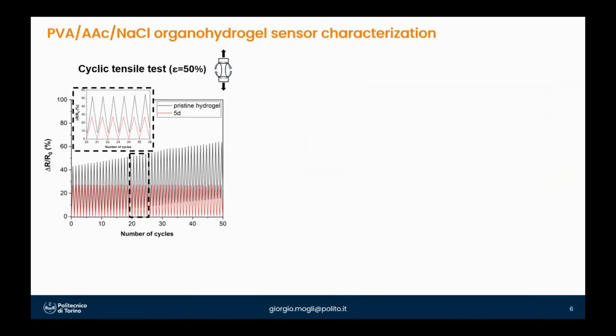Then cyclic tensile tests were carried out to evaluate the repeatability of the measures, and here we can see the comparison between the cyclic test conducted on the organohydrogel and that conducted on the pristine hydrogels. This result showed that the organohydrogel has lower hysteresis, and so lower drift, and allows more repeatable measures.